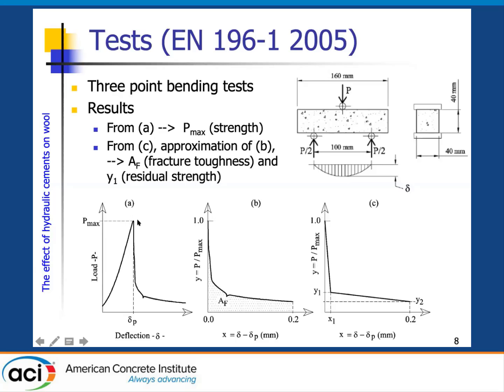P is the maximum load applied to the specimens, and also the deflection at peak of load. With these two values, and of course with the load-deflection curve P-delta, we can define the post-peak behavior. We normalize the load with respect to the maximum load, and we consider only the relative deflection after the peak, delta minus delta at peak, up to 0.2 millimeters.